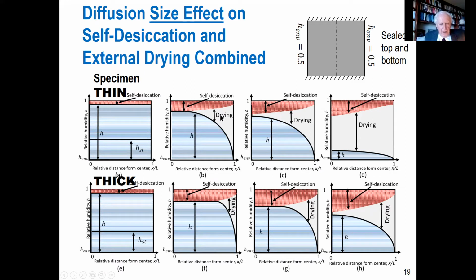So what happens is that as you're drying from outside, hydration is slowed down, so self-desiccation is smaller. Eventually, self-desiccation will not even occur, like here. And the drying propagates in, and soon the self-desiccation will stop, and everything is controlled by drying. So from this point on, self-desiccation doesn't matter. Everything is drying. And it's different in a thick specimen. I show here not a big difference, but it's actually huge. So this goes longer, the stage where you have no effect yet of self-desiccation.